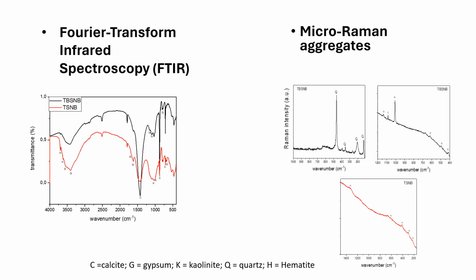In the case of Fourier transform infrared spectroscopy, the TSNB and TBSNB samples present a similar composition with different concentrations of the constituents. They have kaolinite, presence of quartz, and calcium carbonate as calcite, identified from the bands at 1409, 872, and 712 centimeters minus 1. The presence of gypsum comes from the OH bands at 3538 and 3404 centimeters minus 1, as well as from the sulfate bands at 1164, 1114, 668, and 602 centimeters minus 1. The iron oxide is hematite.